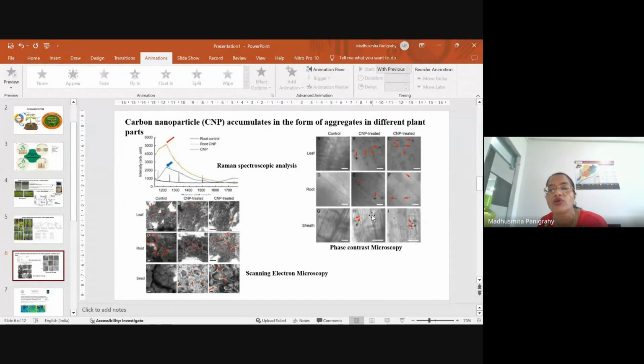After that, we confirmed this also by phase contrast microscopy. We took different parts of the plant like leaf, root, and sheath, both carbon treated and untreated, and we saw that the carbon nanoparticle is forming aggregates in different parts of the plant. And we have also tried this with scanning electron microscopy in the leaf, root, and the seed.